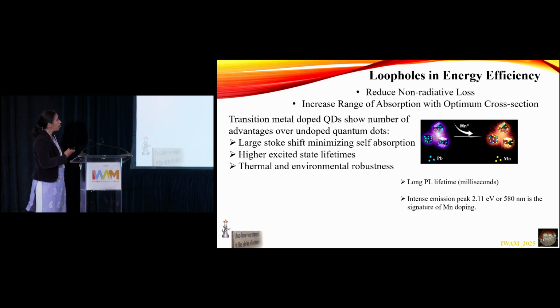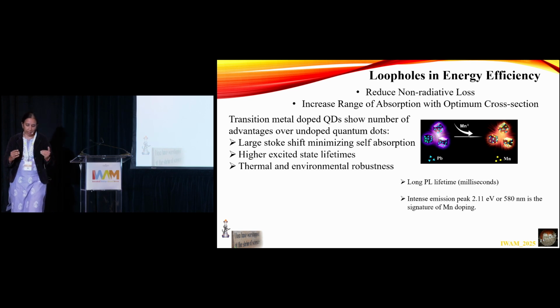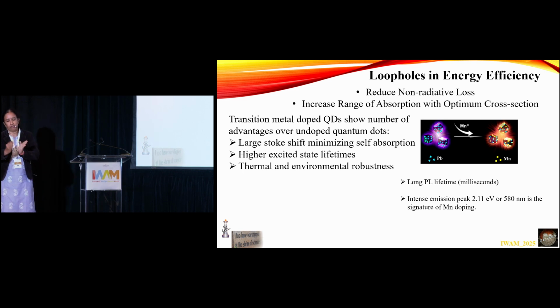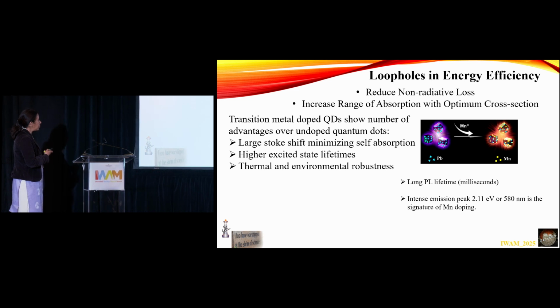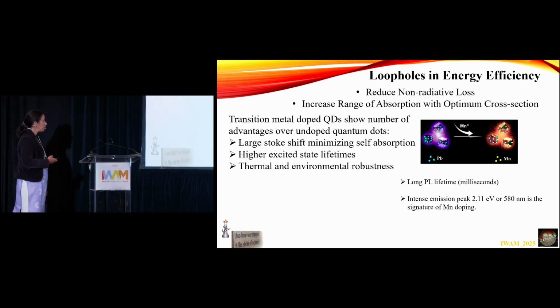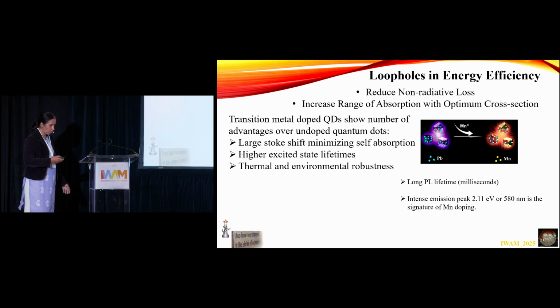So how do we reduce non-radiative loss and increase the range of absorption with optimum cross-section? In II-VI semiconductors, the one thing that has played a big role, and has slowly been taken over into perovskites, is doping with transition metal ions. With transition metal ions, we are talking of a large Stokes shift, which minimizes self-absorption, a higher excited state lifetime because manganese has a forbidden transition, thermal and environmental robustness, and a long PL lifetime, and so on.